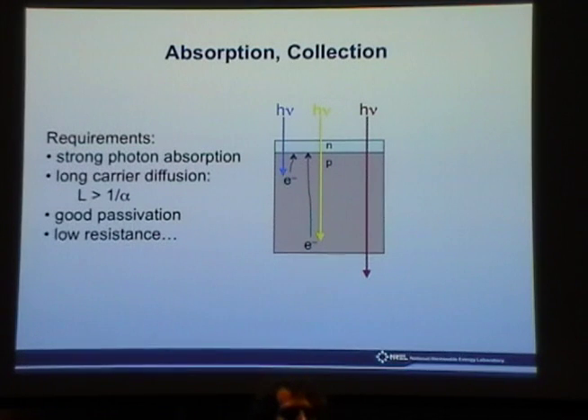There are other considerations to making a good solar cell. You want high absorption, you want high collection. High absorption you get by having direct band gap material, and you want to have as high an absorption coefficient as possible so that you can use as thin a material as possible. So for example, for gallium arsenide, about 4 microns of material will absorb all of the light above its band gap. Anything beyond that, 6 to 10 microns, you're wasting space.